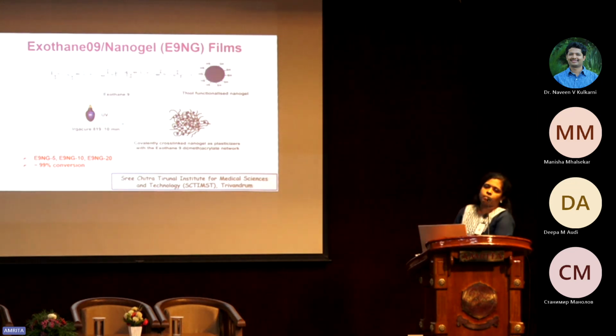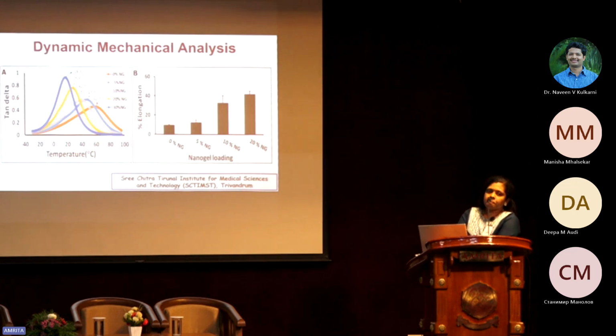And we exposed all the films for 10 minutes, and we checked the conversion by FTIR, and we got more than 99% conversion in all these film samples. And we have represented the samples, the films, like E9NG5, E9NG10, and E9NG20, based on the weight ratio of the nanogel in the matrix or the film. So in order to check the glass transition temperature, that is the crucial characterization in this particular study, we have used the dynamic mechanical analysis technique,